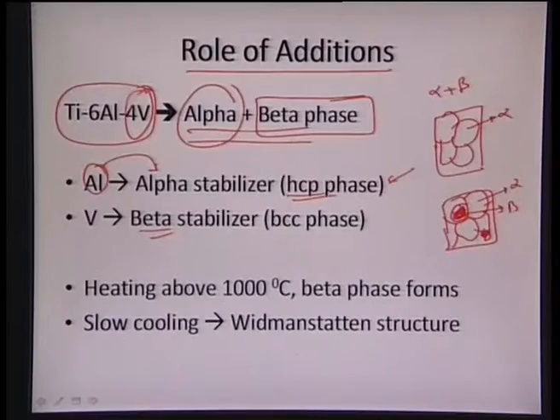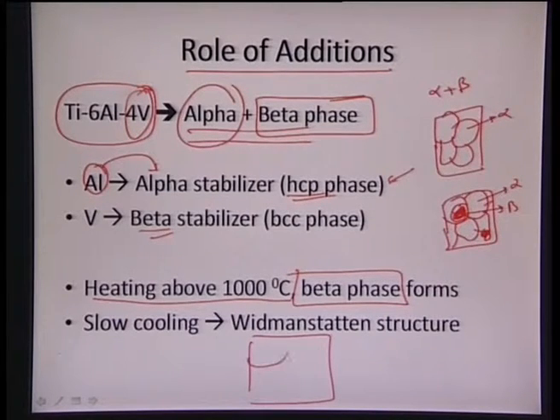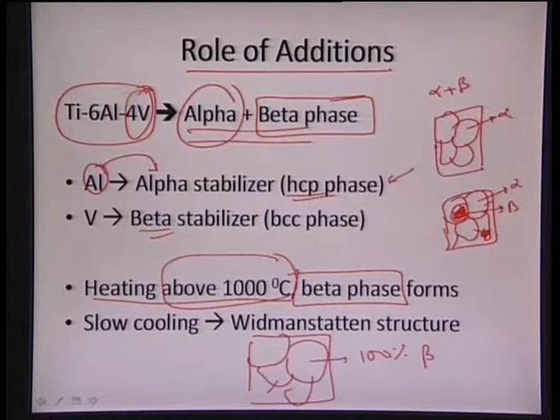So that is the advantage with inducing the secondary alloys such as aluminum and vanadium to impart much more increase in the yield strength and the fatigue strength of a titanium alloy in itself. And one more thing which happens with the titanium 6 aluminum 4 vanadium is that once we heat it above 1000 degrees centigrade, we will see the formation of beta phase, because beta phase is stable at higher temperature. So once we go above 1000 degrees centigrade, we will see a microstructure which is full of beta. So we'll see 100% beta structure which forms once we heat this particular material above 1000 degrees centigrade,